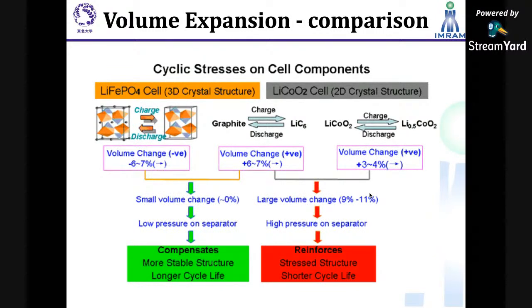So if your material is going to change its shape, as you can see in the case of lithium cobalt oxide, removing 0.5 of lithium gives a volume change of 3 to 4%. Similarly, on the other side, graphite, when you add lithium into carbon, has a volume change of about 6 to 7%. In the case of lithium cobalt oxide, combining these two leads to a volume expansion of 10%.